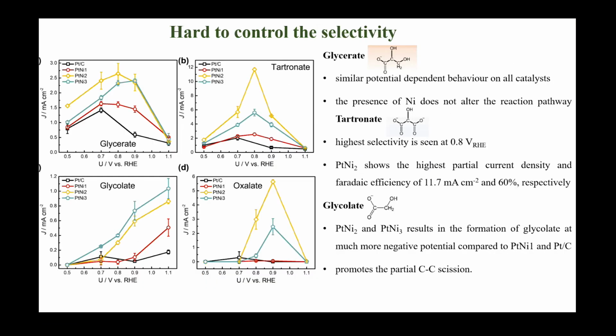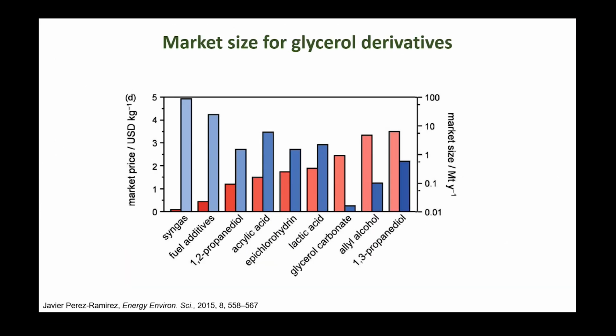But the bottleneck here, no matter which catalyst you work on, as I said, is that platinum gets poisoned quite easily. Platinum nickel 2 shows the highest partial current density and Faradaic efficiency to tartronate, and with platinum nickel 3, the more nickel you have, the more you cleave carbon-carbon bonds and you get to C2 products, but it's very difficult to control the selectivity within these processes.